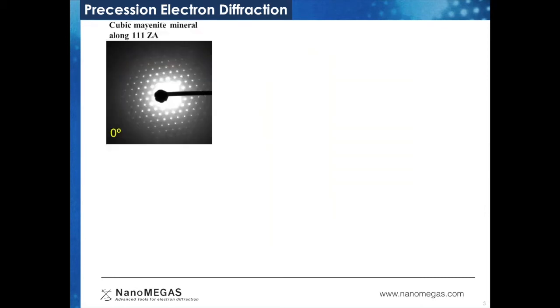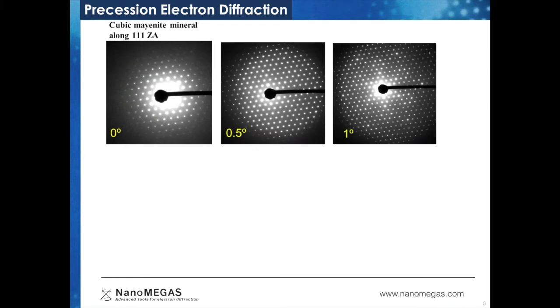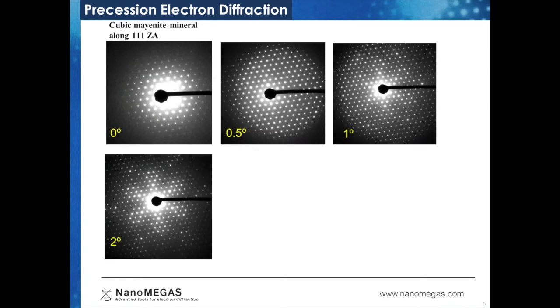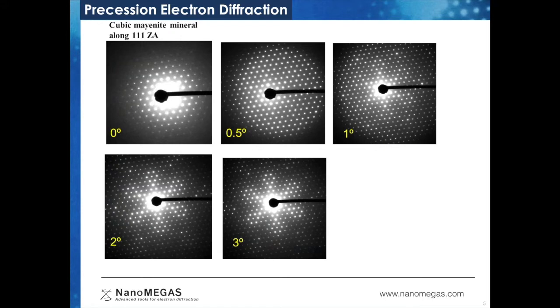Let me show you another example. For a cubic mineral, ED data was collected at different precession angles, and you can see that by increasing the precession angle, the intensity variations in the diffraction pattern die down. Hence, to summarize the benefits of using precession electron diffraction, the intensity variations in the diffraction pattern stay like the kinematical one in case precession is used. That helps in the right symmetry determination, and it helps in the structure solution process.